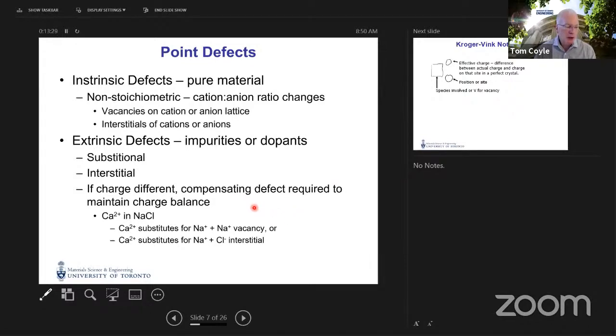Another alternative could be that instead of creating a sodium vacancy to maintain charge balance, we maintain charge balance by creating a chlorine interstitial. So the calcium replaces the sodium, brings along an extra charge, and so we need an extra negative charge to maintain charge balance. And we could do that by putting a negatively charged chlorine ion on an interstitial site, a site not normally occupied in the lattice. Okay, so there's a lot of stuff.